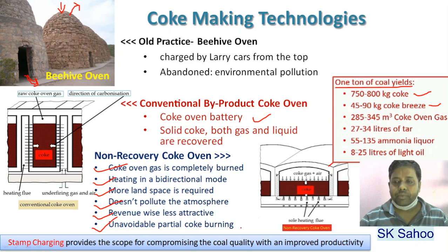Another very innovative coke making process is called the stamp charging process. Stamp charging means what? It provides the scope for compromising the coal quality. That means low quality coal can be used, but without compromising the quality of the coke. How can it be done? In this process, the coking and non-coking coals are blended. A cake is made. That means it's compressed and compacted outside the coke oven plant into a stable briquette